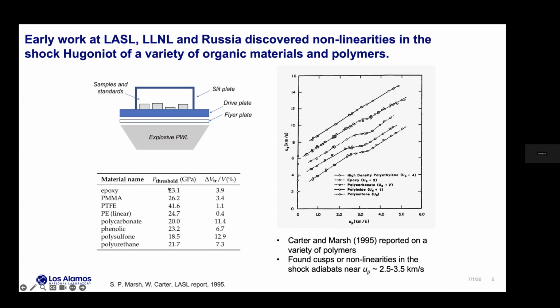And what you see is that most of the polymers have a cusp in the regime where the particle velocity is between 2.5 and 3.5 kilometers a second, which is equivalent to a pressure threshold starting around 20 GPa. And for some materials where there's not a very large cusp, such as PTFE, it's been estimated at like 41 GPa. So somewhere in that 20 to 40 GPa, you would expect that your polymer is no longer a polymer, and in fact, it's a product gas, a solid gas fluid mixture, much like an explosive, and the volume change across those transitions has a lot to do with the polymer structure and the side chain groups.